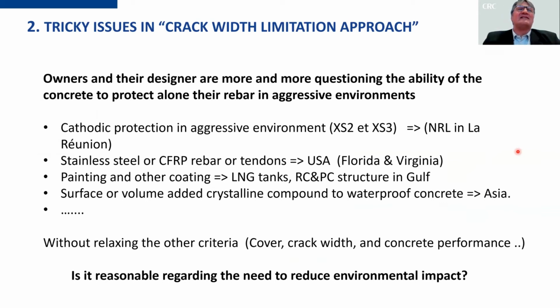But the biggest problem is that the designers and the owners believe less and less in the ability of the concrete to provide protection to the reinforcement during the lifetime of the structure. So they ask for cathodic protection, for example, in the Nouvelle Route du Littoral in La Réunion. They ask for stainless steel rebar, or even stainless steel tendons, or even carbon fiber reinforced rebar, for example, in Florida. Or they ask to paint the structure, like in the Gulf or in the petroleum industry. Or sometimes you have to add some various compound, like a crystalline compound or powder of perlimpinpin.